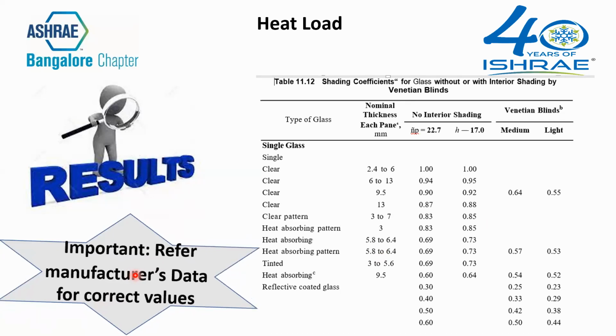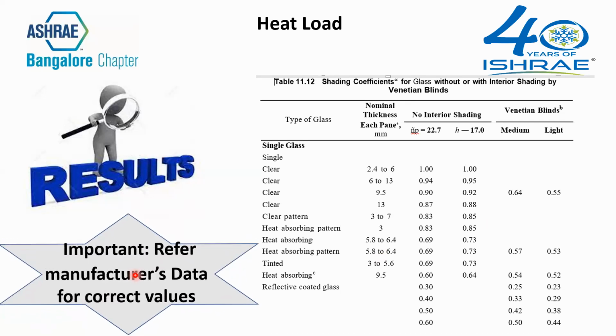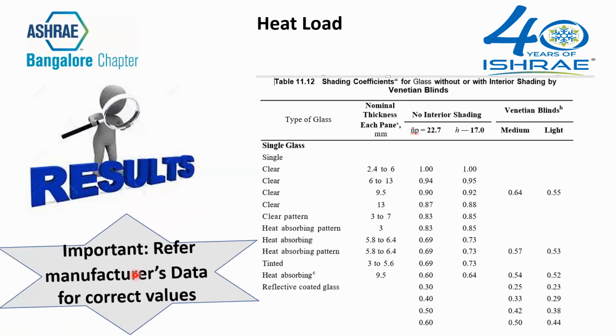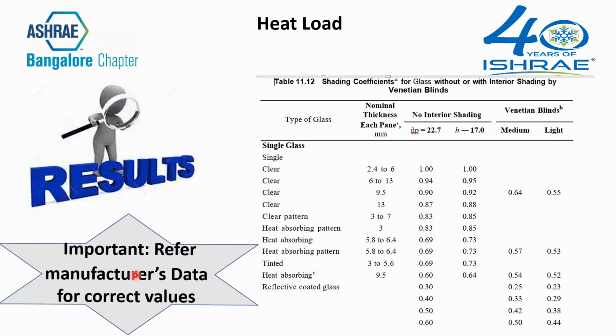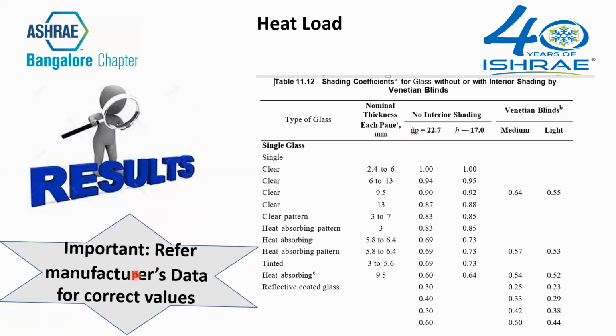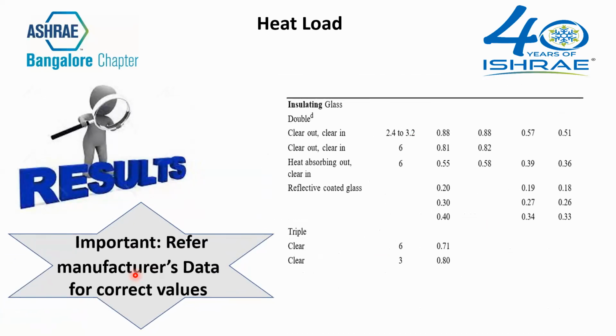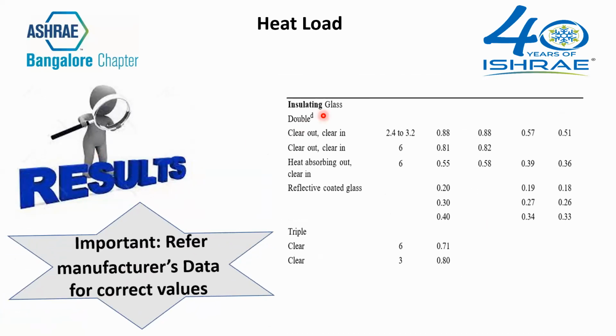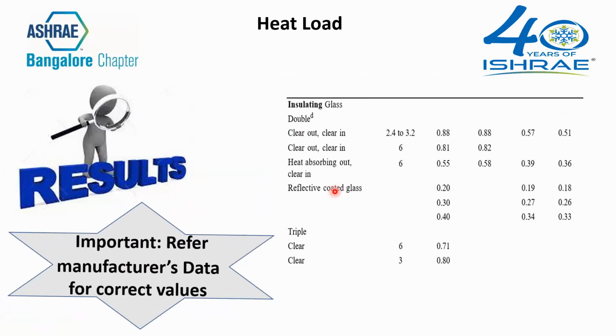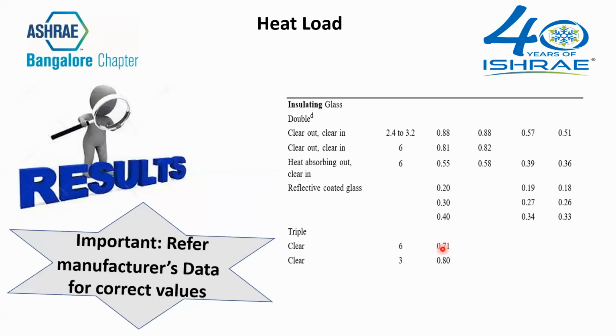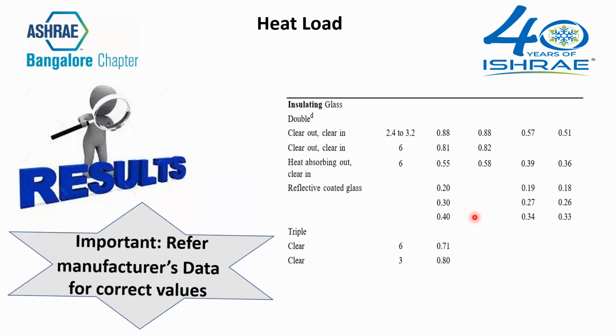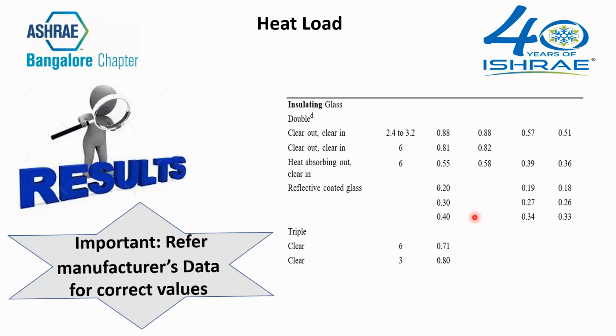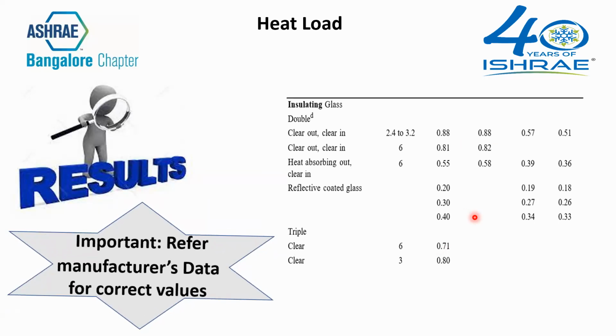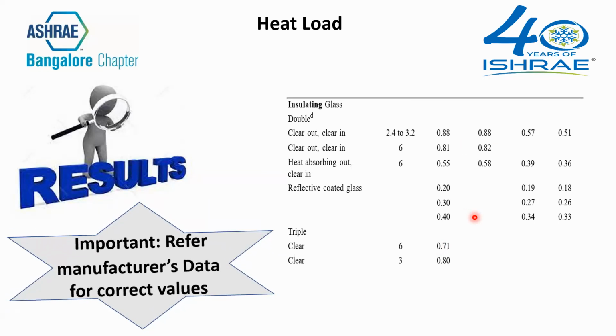You will have to refer to the glass manufacturer's data, where it gives you the correct value of reflective, we call it as the K value. It gives you the correct value of thermal conductivity, which needs to be considered. Then, when you have, say, clear glass, you have coated glass, based on the coating, or whether it is double coating or single coating, two pane or double pane, your K factor varies, or your watt per square meter varies. So this is very, very important for us to understand, that we need to look at the manufacturer's data also, that is the glass manufacturer's data, to get the correct K value or the factor for us to consider.